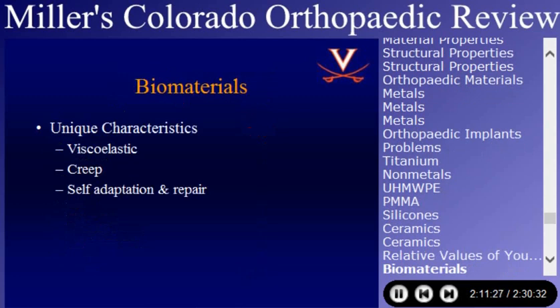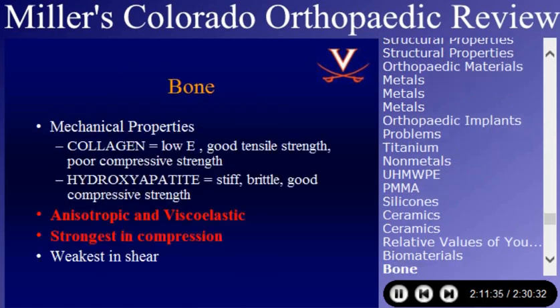Some of the unique characteristics of biomaterials: they're viscoelastic, they undergo creep, and they have the ability for self-adaptation and repair. Let's talk specifically about our favorite, bone. Mechanical properties. The collagen has low stiffness, but it has excellent tensile strength and poor compressive strength. But the hydroxyapatite portion of bone is stiff, has a very high Young's modulus. It's brittle, and it's good in compression. Bone is anisotropic and viscoelastic. That's another question for you. And it's strongest in compression and weakest in shear.